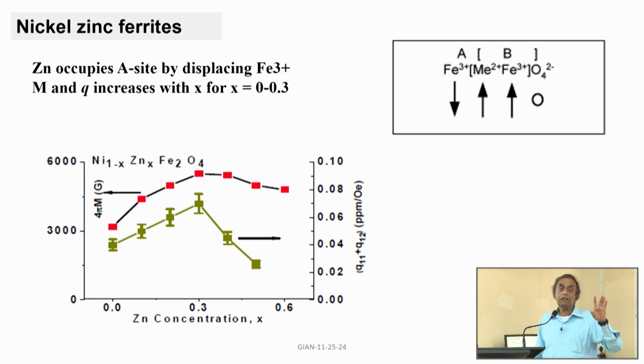Take it for granted that if I substitute zinc in nickel ferrite or cobalt ferrite, two things happen. One is there can be an increase in the magnetization and in the magnetostriction for zinc substitution up to 0.3. So, these are preferred compositions for use in some of the composites.